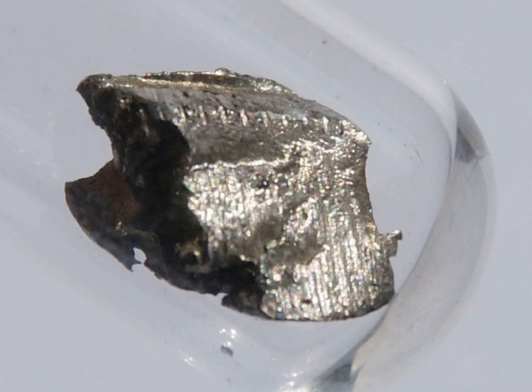Upon cooling below minus 15 degrees Celsius, gamma cerium starts to change to beta cerium, but the transformation involves a volume increase and, as more beta forms, the internal stresses build up and suppress further transformation. Cooling below approximately minus 160 degrees Celsius will start formation of alpha cerium, but this is only from remaining gamma cerium. Beta cerium does not significantly transform to alpha cerium except in the presence of stress or deformation. At atmospheric pressure, liquid cerium is more dense than its solid form at the melting point.